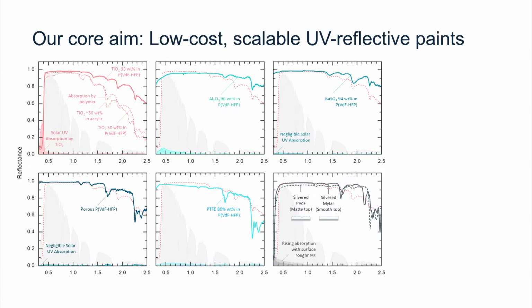And this is a very, very strange kind of thing. And if you talk to folks in the traditional paints and coatings industry, they would be kind of surprised if your goal was not to absorb UV, right? That is the dominant paradigm we see for outdoor materials. And so our approach initially was to simply replace the pigment with a UV reflective pigment, which is, say, a UV non-absorbing pigment. And so our two candidates are shown at the top right there.